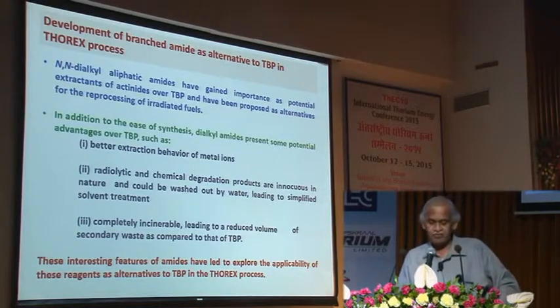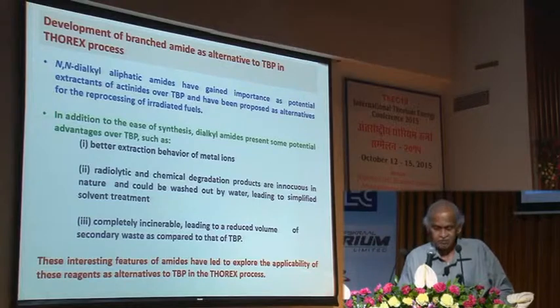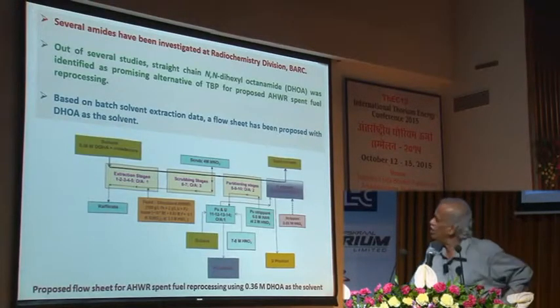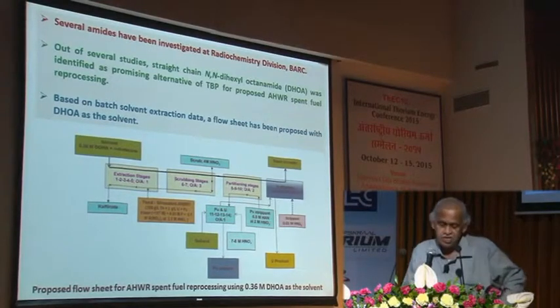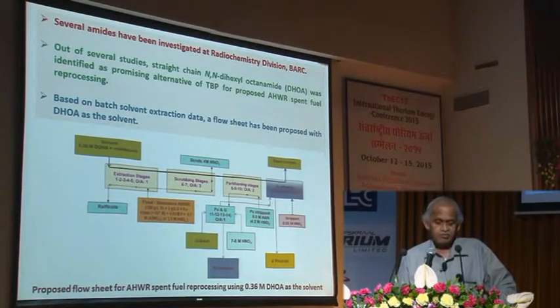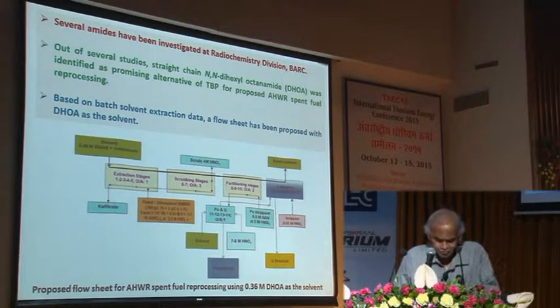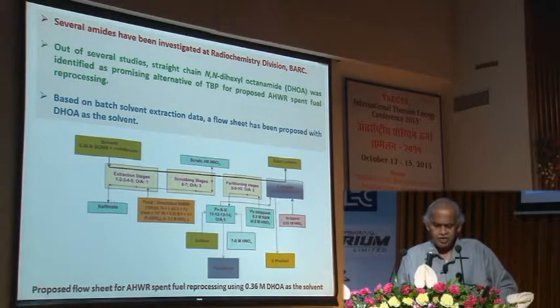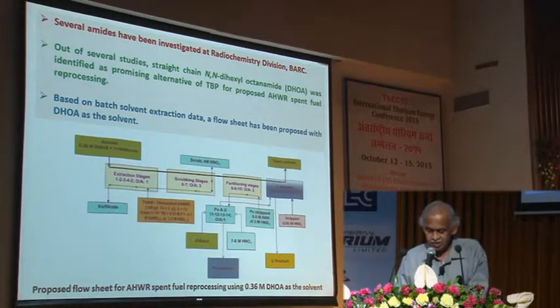These interesting features of amides have led us to explore the applicability of these amides as alternatives to TBP in the THOREX process. This is a simple amide process which has been developed. Of course, we had the pleasure of collaboration with the nuclear recycle group in extending these studies further, and we were able to show that DHOA, di-n-hexyl octanamide, was identified as a promising alternative to TBP for proposed AHWR spent fuel reprocessing, and this is the typical flow sheet which we thought we would be able to use.